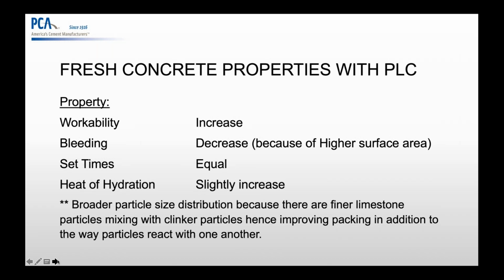As far as fresh concrete properties, the workability increases, the pumpability also. We've seen some improvement in the pumpability of the concrete. Bleeding decreases, that's due to the higher surface area of the particles. Set times are pretty much equal. Heat of hydration slightly increases, but again, that can be mitigated with any type of SCM, especially slag.